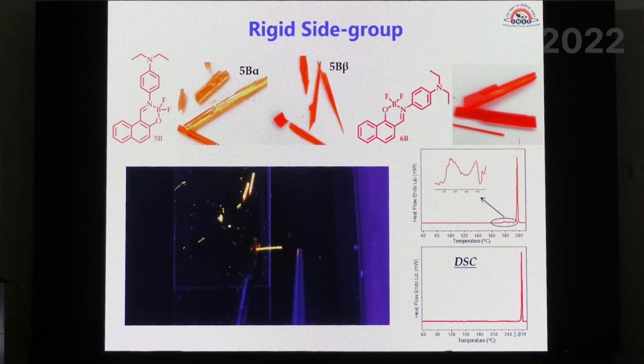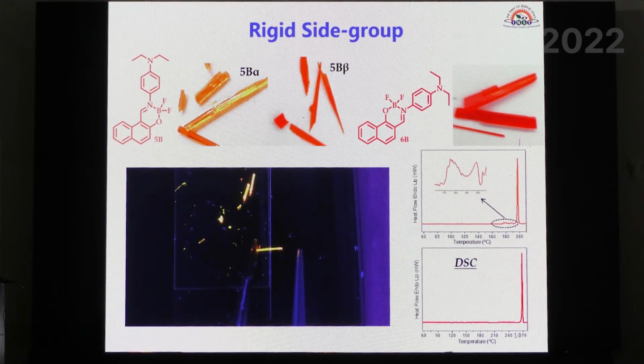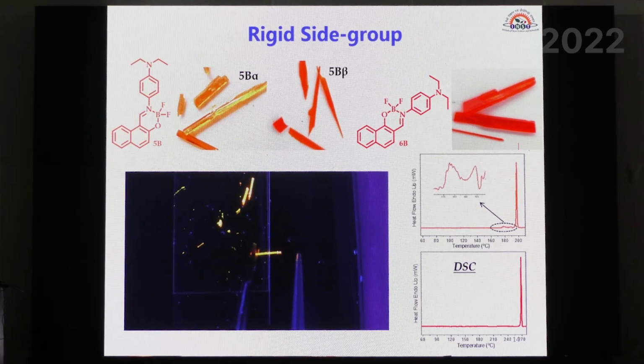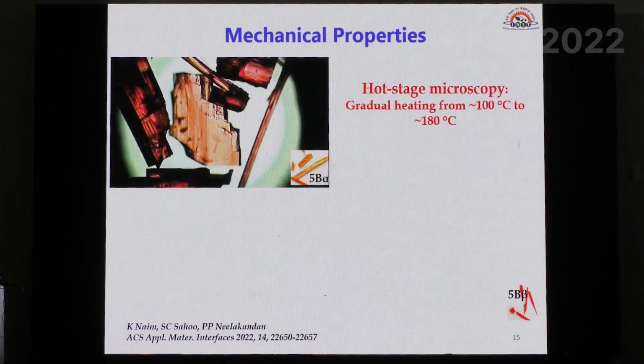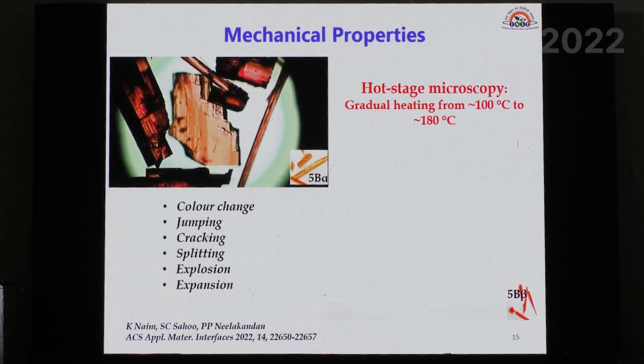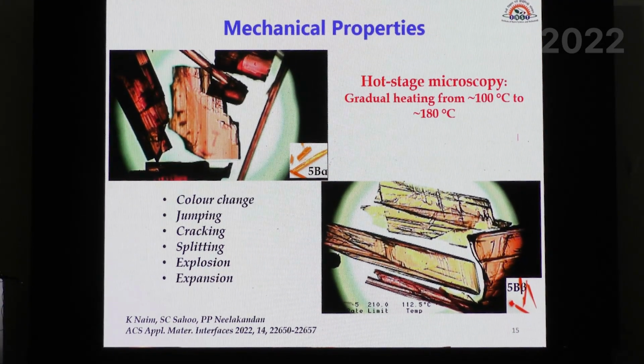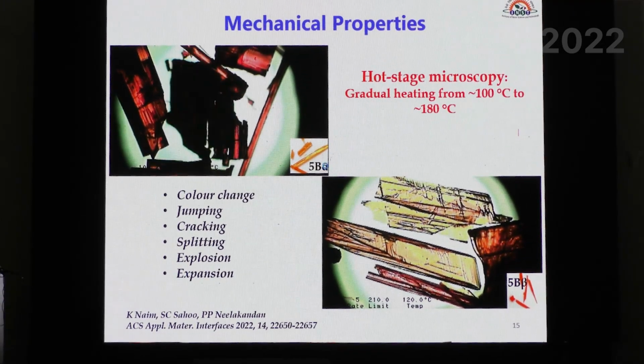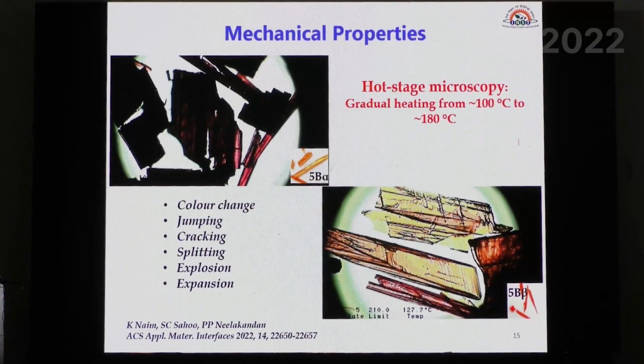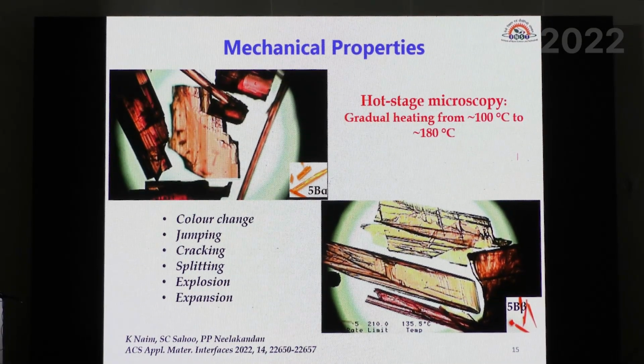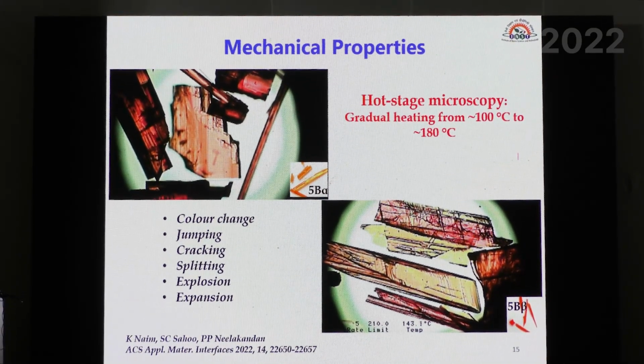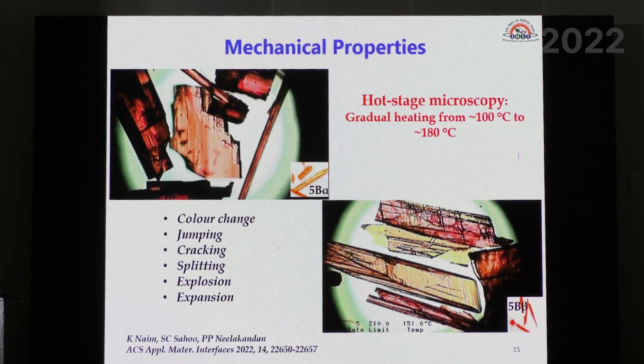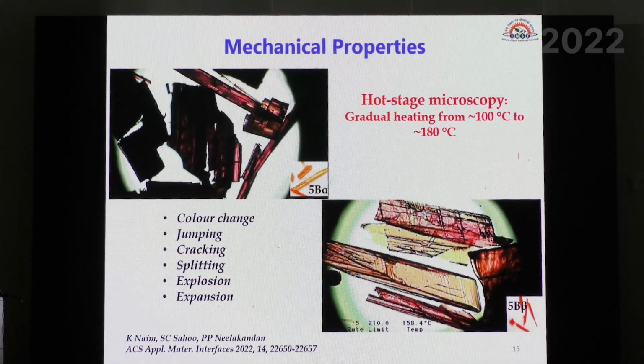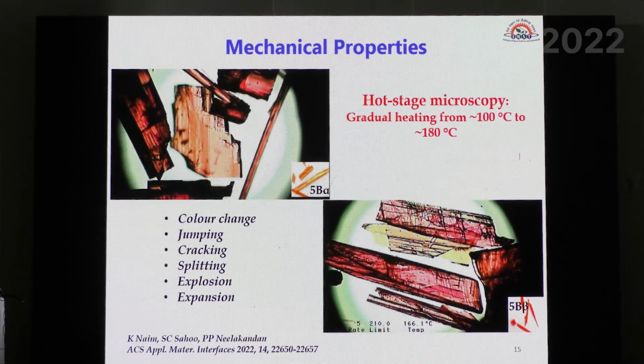So what we did was we looked at this process, heating this material under a microscope. This is a hot stage microscopy video for these compounds. You can see this compound, when you start heating it, say above around 110 to 120 degrees, slowly it starts to change color, and then it breaks, and some of them even bend. So we see all these features here.